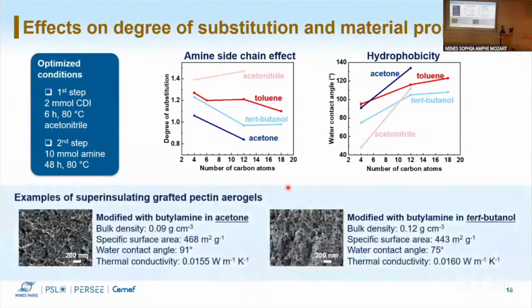Some examples of materials that were super insulating and with increased contact angle: modification of the aerogels in acetone and tert-butanol. So with butylamine in both cases, here in acetone, here in tert-butanol. In both cases, we have low density, we have high specific surface area, very close to our neat materials. Contact angles are increased a lot. Here we're almost hydrophobic. And the thermal conductivity remained very low, as low as we have for neat pectin aerogels.